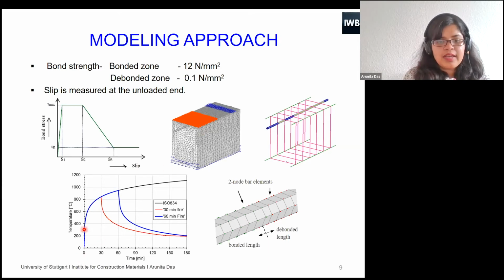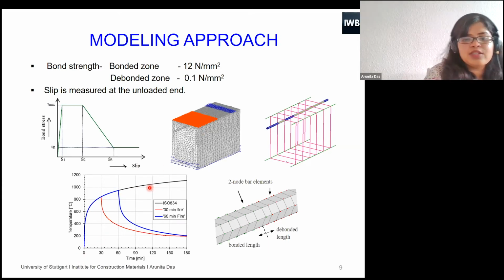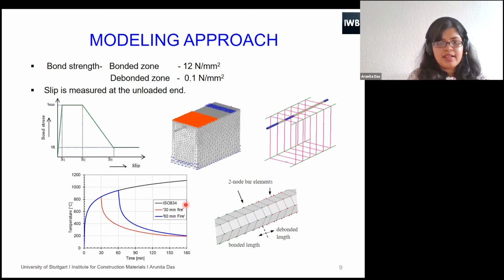This black line here is the ISO 834-1 fire curve, which is the realistic fire curve which we have considered in our study. As I have mentioned, we have considered 15 minutes of fire, 30 minutes of fire, 60 and 90. Here I'm showing 30 and 60. 30 is this red line, 60 is this blue line. It is following this curve. Here we are switching off the burners, and then it's coming down, and this is how it is following during cooling down.